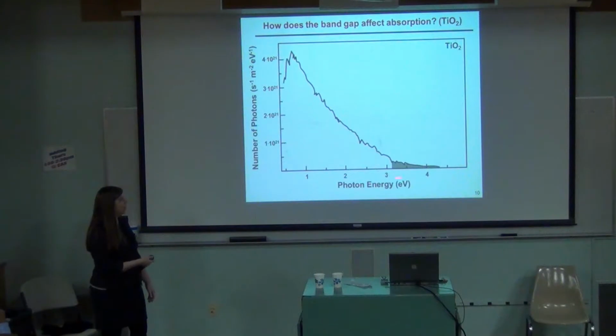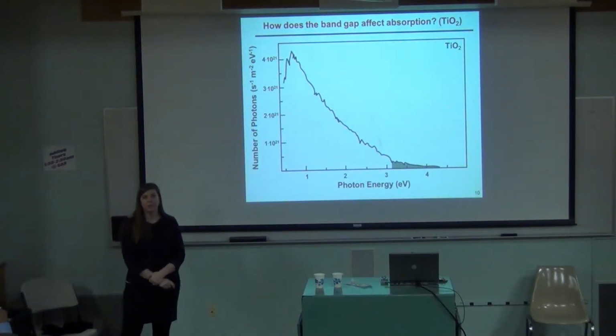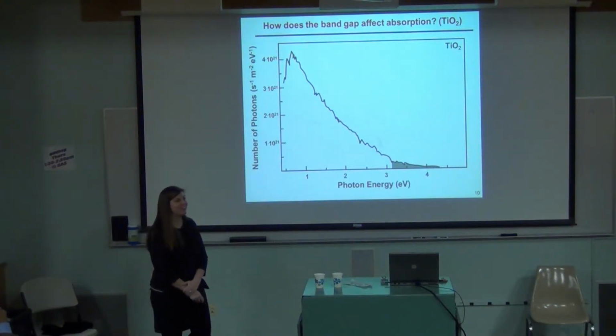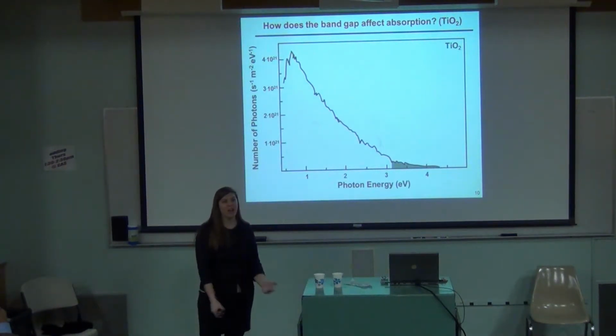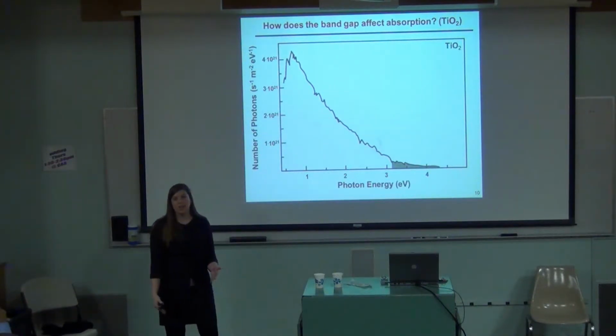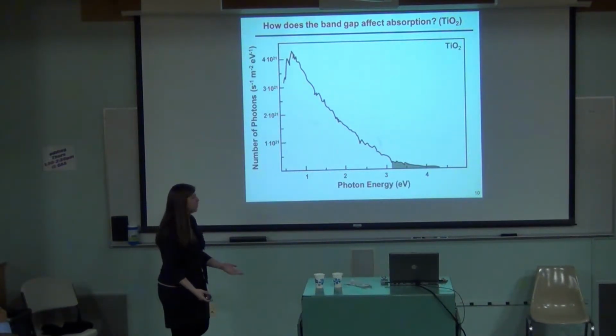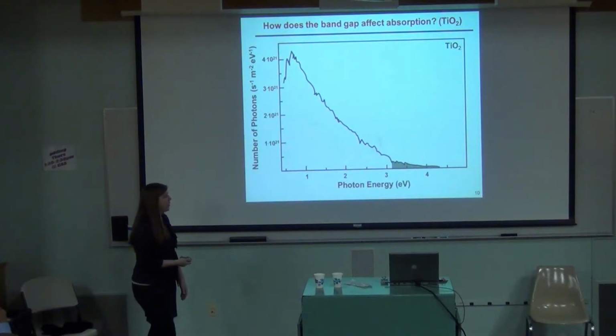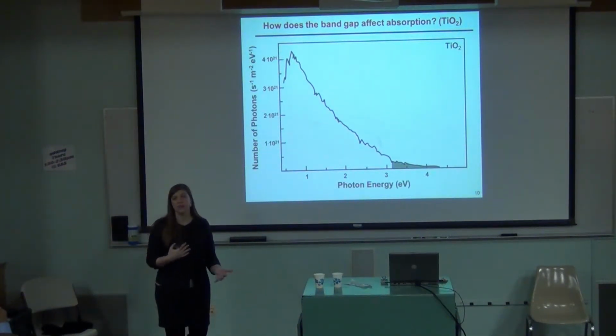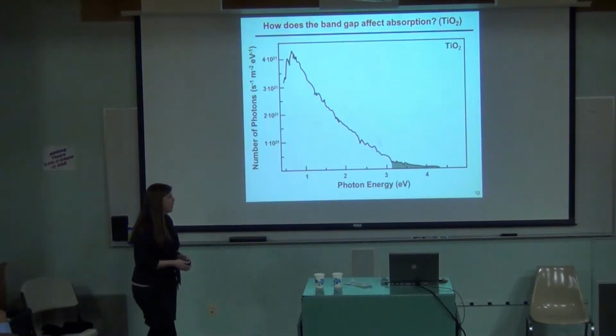This is how much of the sun it can actually utilize. Pretty pitiful. There's not much there. So that means that even if you have a lot of titanium dioxide, its efficiency is terrible. And so it's been used in some photovoltaics, but they have to use a lot of dyes, and they have to couple it with things, and they have to use a catalyst and a lot of other things that may not be inexpensive, so it's not necessarily the best.